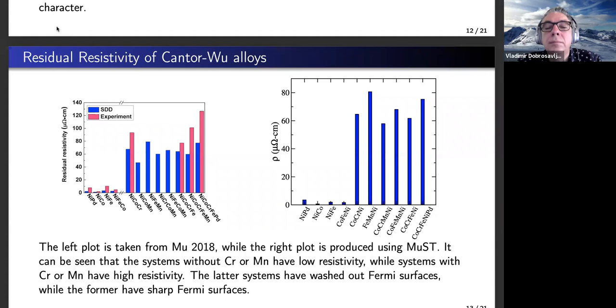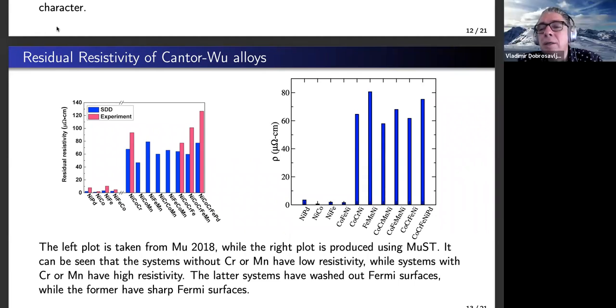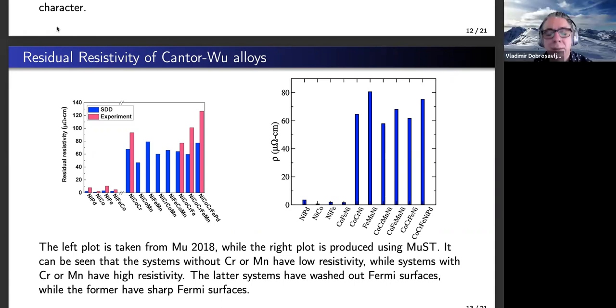Right. But it turns out, in the KKR-CPA, you can say, aha, I don't like this. Can I find another solution? And one other solution is that half the manganese point up and half of them point down. That's just like an extra component. Then you do that, and what you find is, in fact, a magnetic ground state with half the manganese up and half down. And that state corresponds pretty closely to what you see in the supercell calculation, because again, about half of them are up and half are down. So this is the same as doing some mean field theory of spin glass ordering.